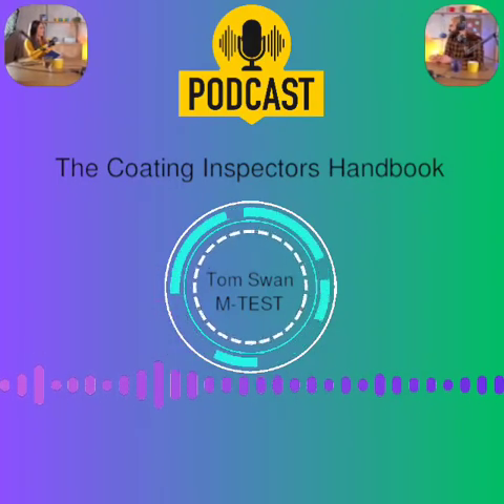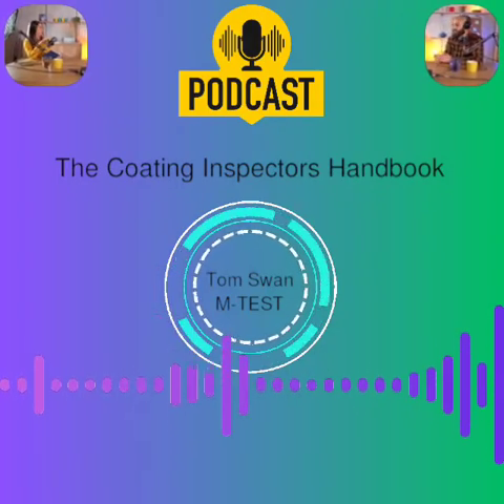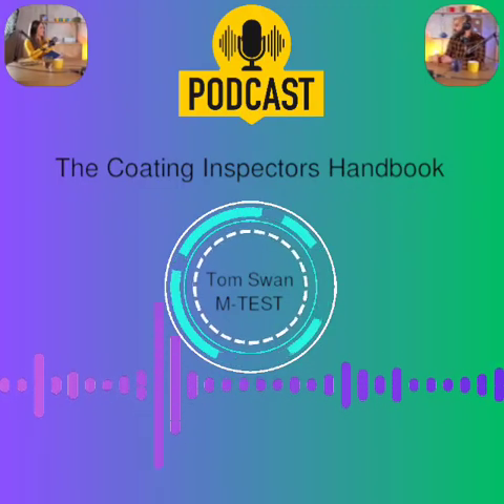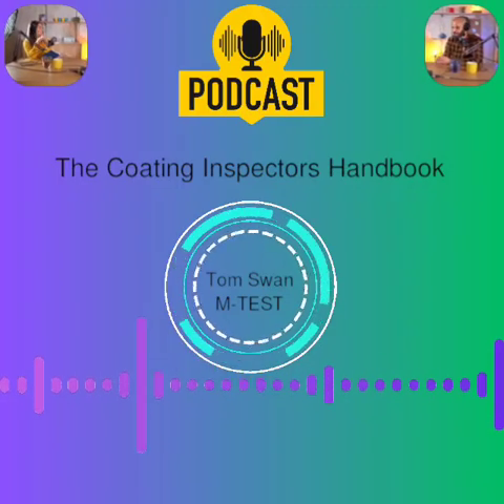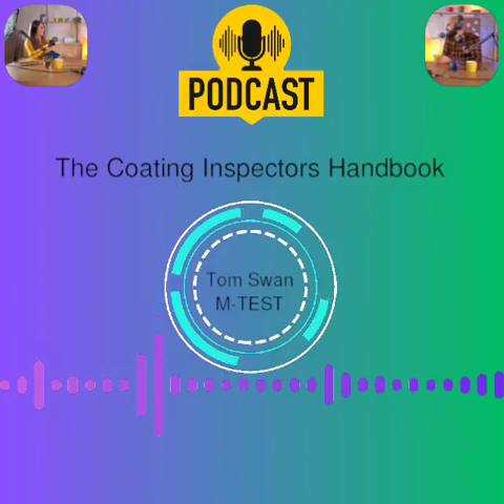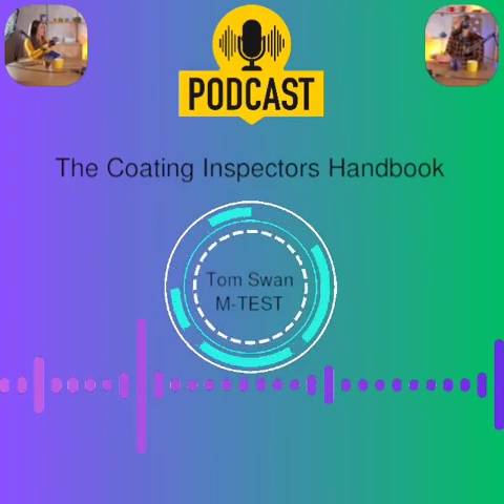And how much salt do these methods actually pull off the surface? Extraction efficiency. Yeah, that varies. SCAT might only get around 25%. Bresle, if done well with good massaging, can get maybe 40% to 80%. It's important to run a blank test too. Check the patch and water for contamination. Yeah, the other salt tests.